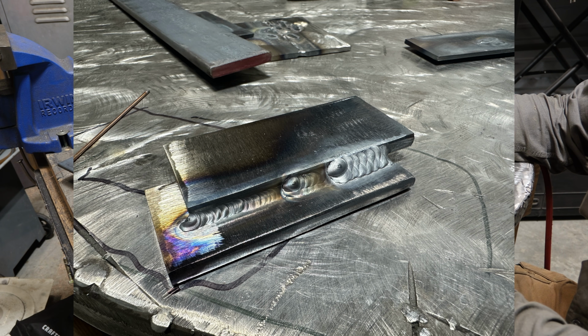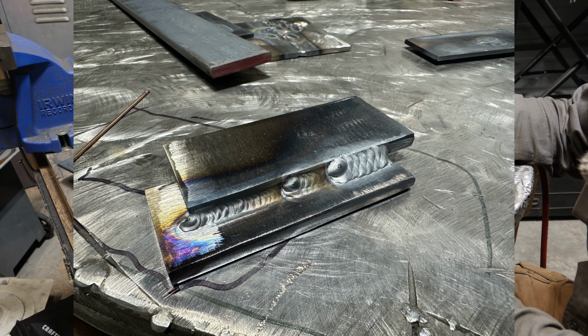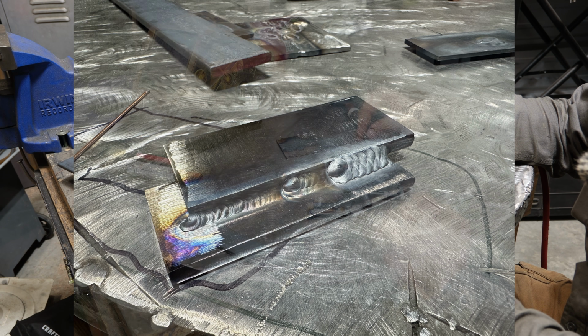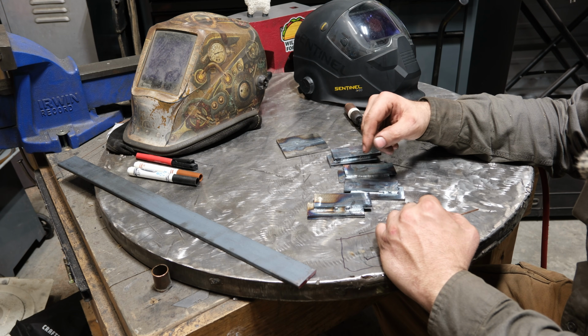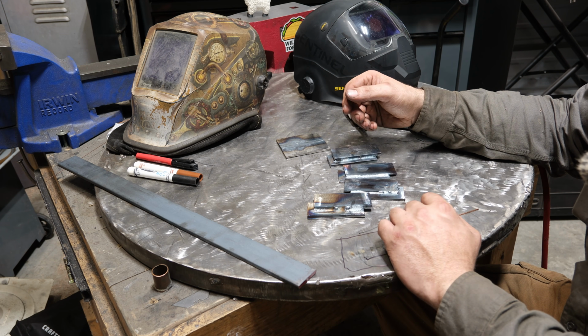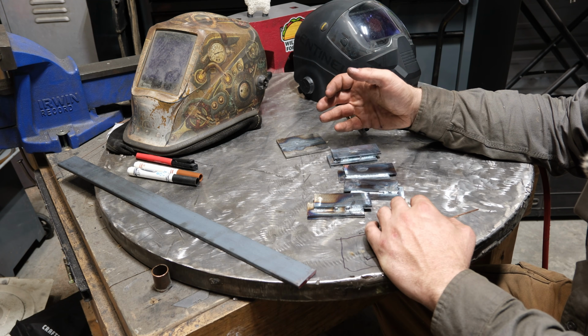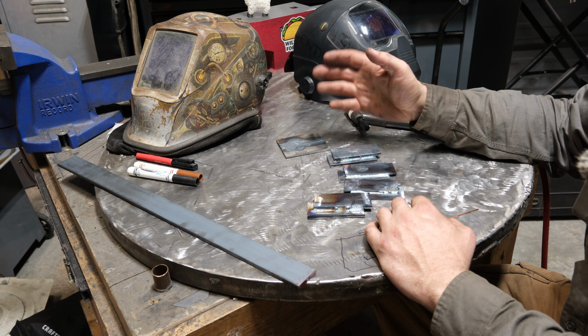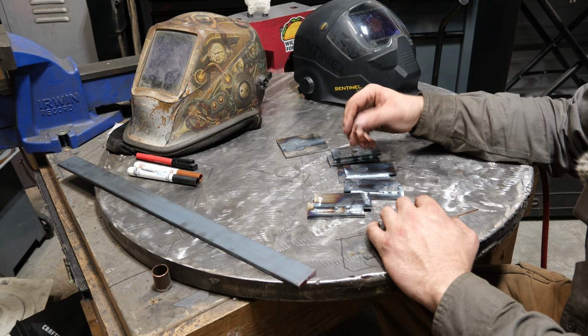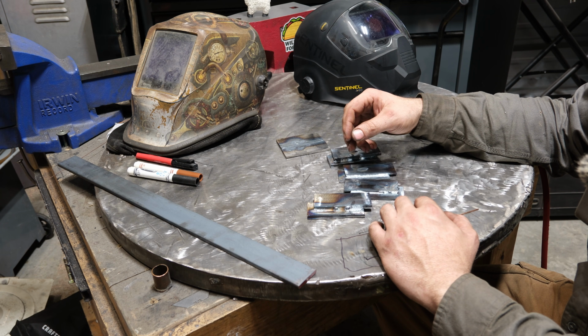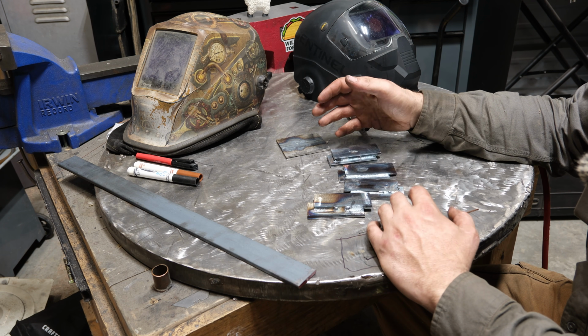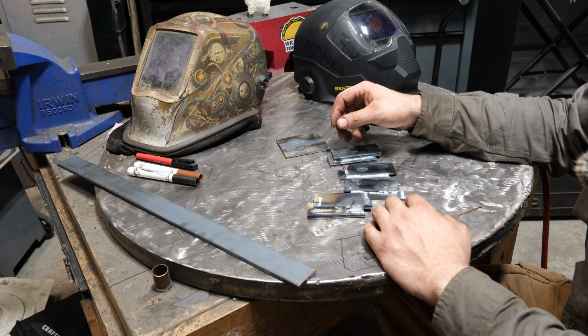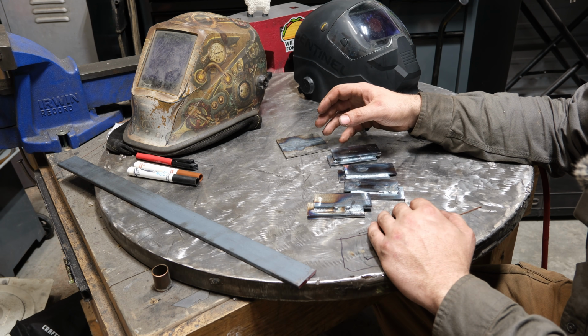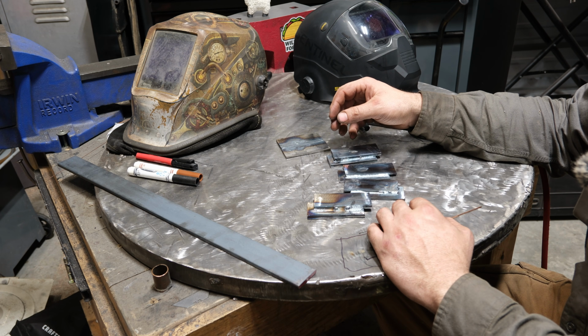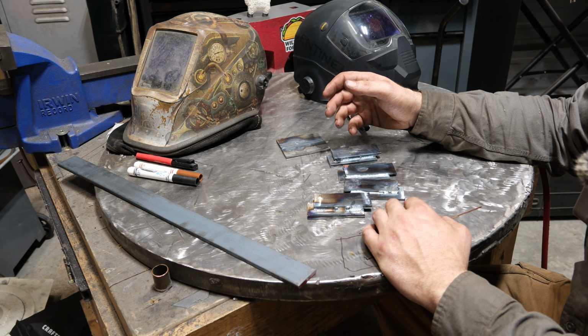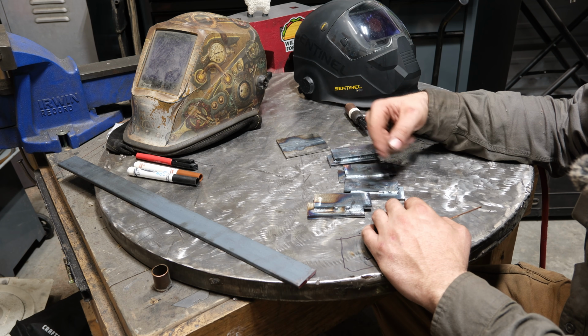Now, I'll be honest with you guys, when I'm welding 1/4 inch, universally, I'm not TIG welding it for a lap weld. I'm probably spray arc welding it or stick welding it. And the reason's simple. TIG is so slow. And I welded that at about 150 amps. If I had cranked it up to 200 and used even bigger filler rod, I only had 1/16 handy. If I had used 3/32 at 180 to 200 amps, I could have done that in 3 passes. No problem, even 2 passes, just a root fill and then a cap.